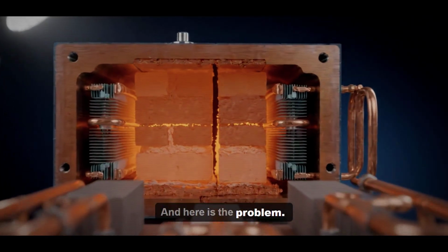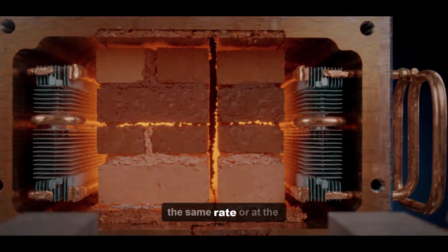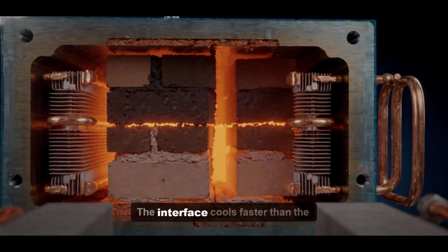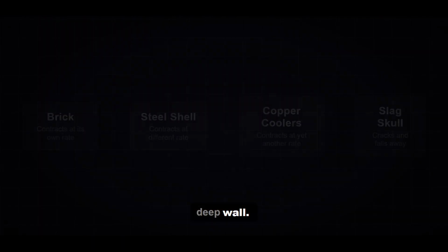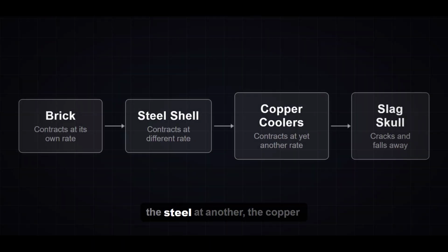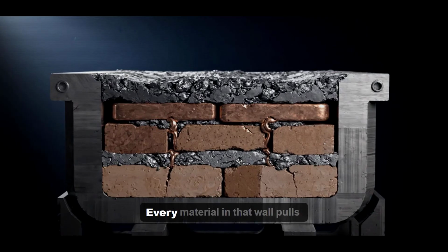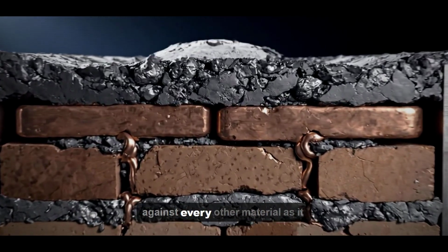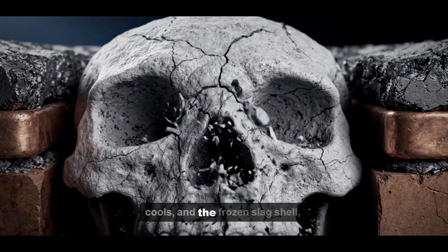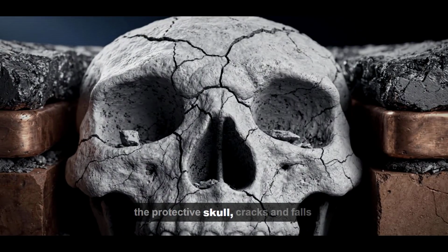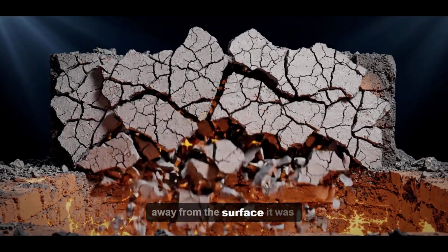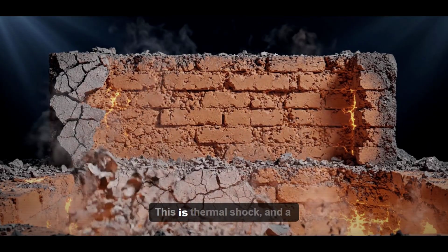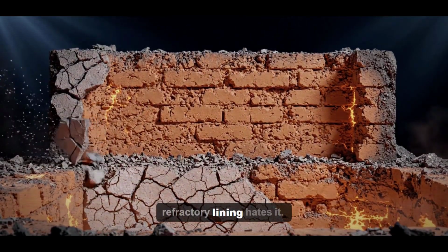And here is the problem. It does not all shrink at the same rate or at the same time. The interface cools faster than the deep wall. The brick contracts at one rate, the steel at another, the copper at another. Every material in that wall pulls against every other material as it cools, and the frozen slag shell, the protective skull, cracks and falls away from the surface it was clinging to. This is thermal shock, and a refractory lining hates it.